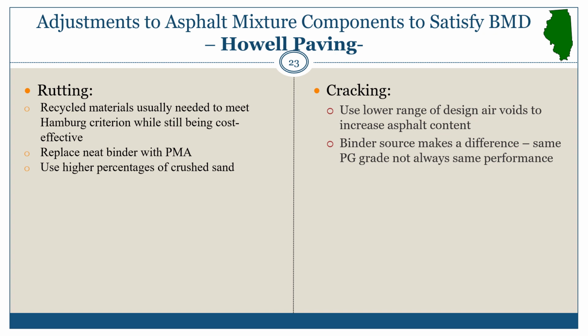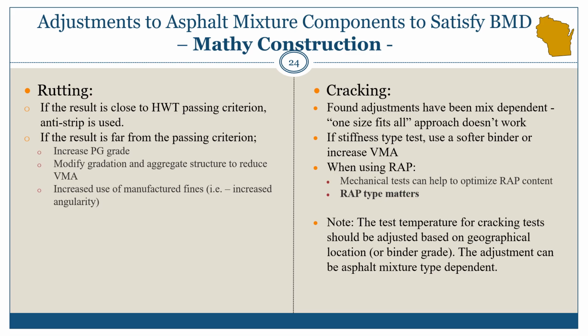With Andrew Hands at Mathy Construction, what Andrew discovered is that if the result is close to passing the Hamburg criteria, it may not necessarily be rutting, but maybe some of the stripping potential of the material. You can make that material pass if you utilize an anti-strip. There's that coupling of effects between rutting and stripping potential in the wet Hamburg wheel tracking test. If the result is far from the passing criteria and an anti-strip won't help, what Andrew found is you have to increase the PG grade.